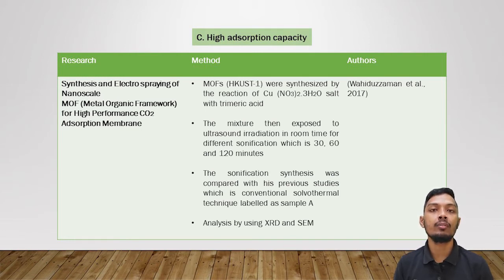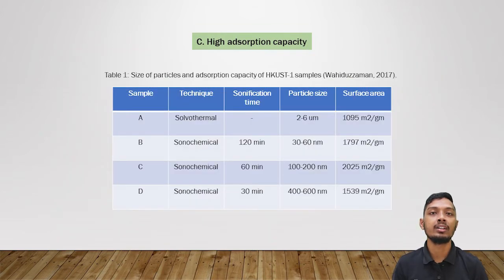The characterization of copper-based metal organic framework is then carried out by X-ray diffraction and also scanning electron microscopy. The result of sonication synthesis is compared with a previous study, which is conventional heating, to compare the absorption capacity between those methods. The result revealed that copper-based metal organic framework prepared by sonochemical technique has larger surface area compared to metal organic framework prepared by solvothermal technique. Overall, it can be said that copper-based metal organic framework prepared by sonochemical technique is better compared to the one prepared by solvothermal technique.